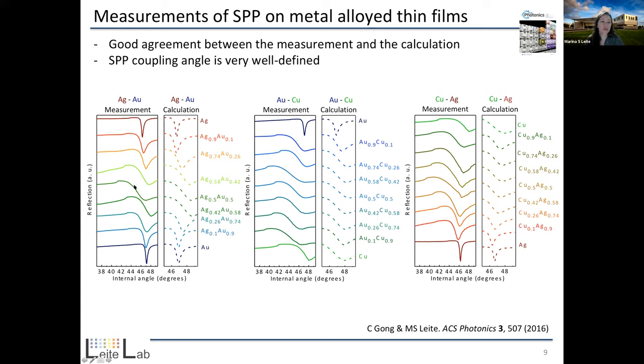So these measurements here and the calculations show us that first of all, we do have a very good agreement between the two. Second of all, we see how smoothly this minimum in reflection occurs in the case of silver and gold. And then for the other combinations, that's not so smooth, right? We see that we have quite a bit of loss here.